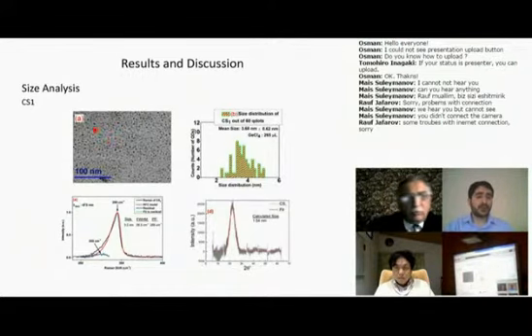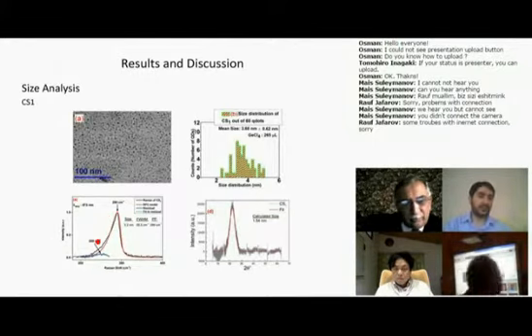Okay, let's talk a little bit about the results. First of all, for the first method, in order to understand what we produced, I took transmission electron microscope pictures. As you can see from the picture, there are spherical particles. The size distribution is about 3.6 nanometers. I also took Raman spectra to understand what it actually is. This is a very nice asymmetric germanium peak, which is around 290. This asymmetric peak tells us they are nanoparticles. If it were not asymmetric, it would be hard to believe that it's a nanoparticle. We also see this from the picture.